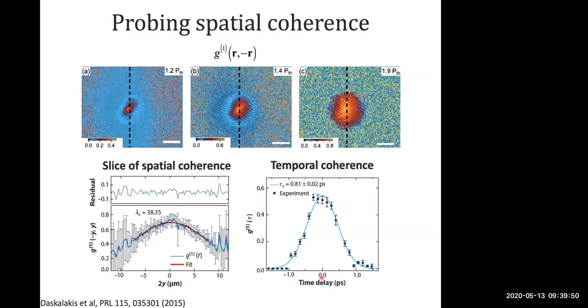In this sort of situation, you can also get the temporal coherence for free. So here, the temporal coherence, which you get from looking at the decrease in visibility of the Michelson, just like you would use a normal Michelson, is on the order of 1 picosecond. And this 1 picosecond is simply the duration in time of that condensate emission burst, because in all of these experiments, we always pump impulsively. So we pump with a short pulse, we populate a reservoir of dark excitons, these scatter to populate polaritonic states, but once that reservoir is depleted, there is no more condensate emission. So this 1 picosecond corresponds very closely to the calculated duration of that condensate emission burst. Okay.